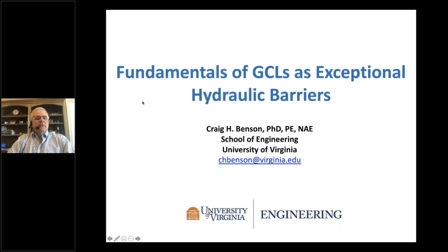And Roberto Ronson asks, why do we see specifications that require a confining stress to be placed over GCLs immediately after installing the GCL? Is this confining stress material really necessary? That's a good question. It's not necessarily confinement, but it is for protection. Once we get the GCL in and the geomembrane in, we want to get it covered. As soon as we place the GCL on a subgrade, geomembrane on top of it or not, it begins to hydrate. It begins to draw moisture up from below. If we don't have it protected with a geomembrane and it rains, we get moisture in from above.